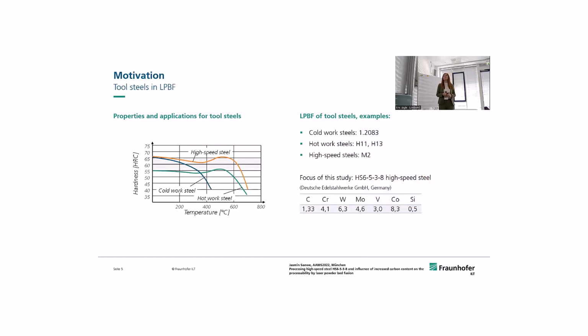Generally, high-speed steel as a tool steel is very interesting for a lot of applications. We heard about work on different tool steels, namely hot work or cold work steels, also investigated in laser powder bed fusion. But high-speed steels have the advantage of very high hardness and temperature resistance up to 600 degrees Celsius, and they have been investigated in the past. The material that I'm focusing on today is HS6-5-3-8. It's a random number you might think, but if you look at the chemical composition, mainly the carbon content is interesting because it's already 1.3%.